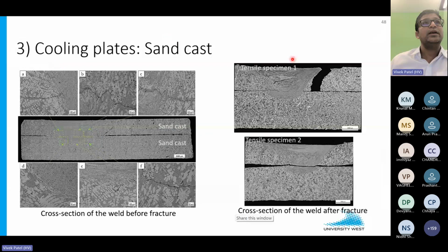Then also sand cast, similarly, you can see the cross section, and we tried to understand the different features of lap joints, hook and cold lap. And you see that the sand cast basically behaved differently. Here you see it's failing almost near the heat affected zone, not on the weld nugget, but in some of the tensile specimens we found that it's opening from the weld nugget itself. That's basically due to a lot of large voids and the dendritic structure of the cast material, and there is a lot more to do for sand cast when it comes to friction stir welding.